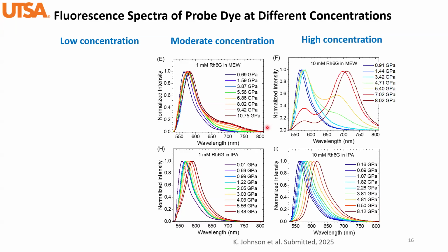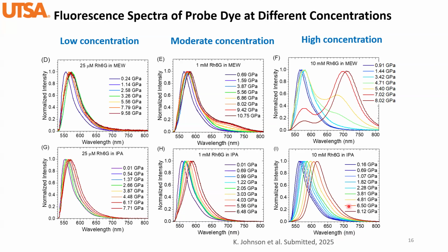So to confirm our guess, we carried out the study under a higher concentration of the dye, and this is no longer a shoulder, but becomes a dominant peak for the aggregates emission. But in this case, if you consider a higher concentration of dye molecules in IPA, this peak does not pop up, and at lower concentrations we do not see this either. So that means this peak is from aggregates, and it's also solvent dependent.